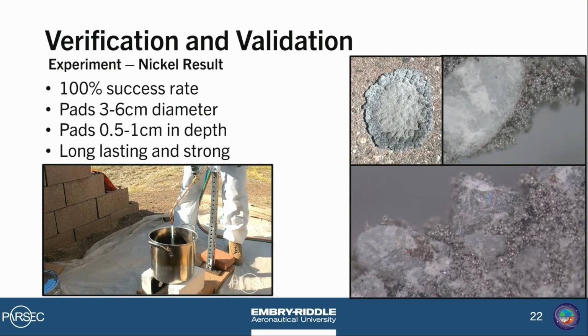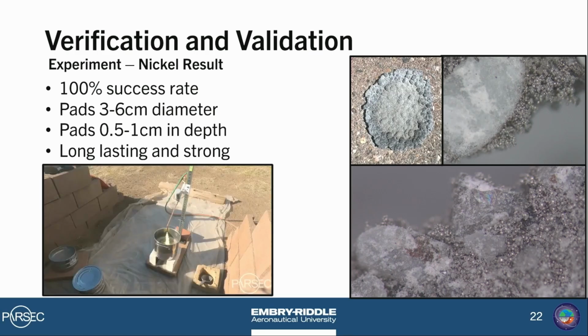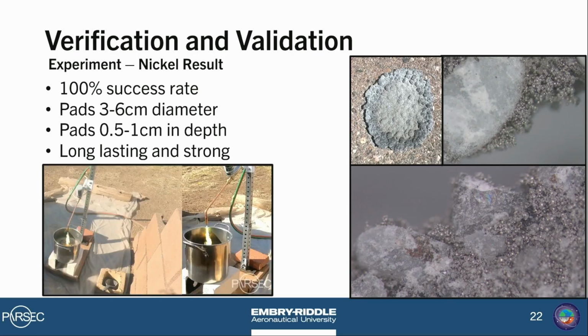Our second additive that we tested was Buildup 22, manufactured by Victor, and that is a nickel alloy additive. As opposed to the alumina, this additive achieved a 100% success rate in conglomeration on all 8 of our tests, conglomerating no matter the surface, whether it was directly on a fire brick, on sand, or on LSP2 regolith simulant.